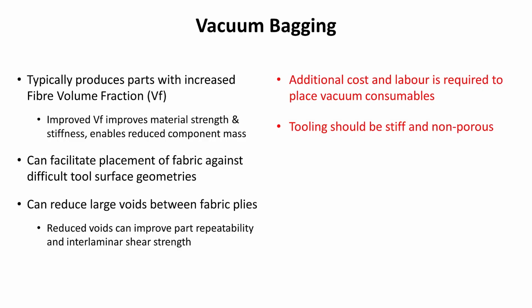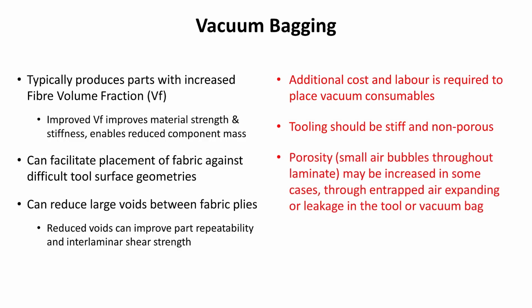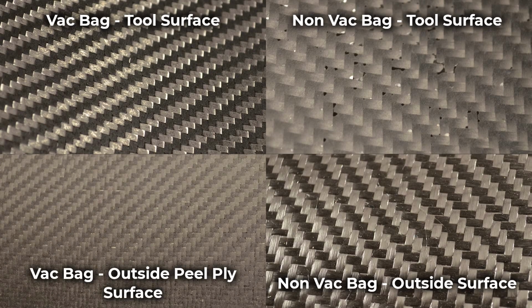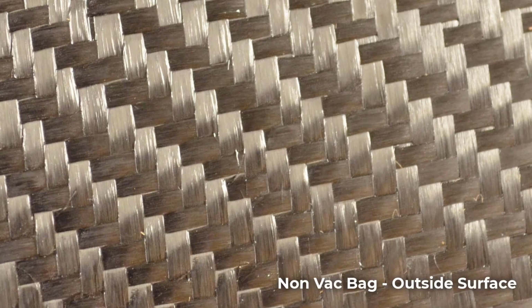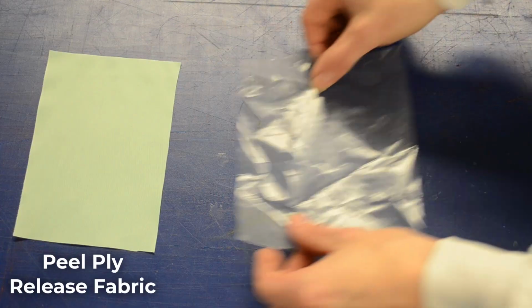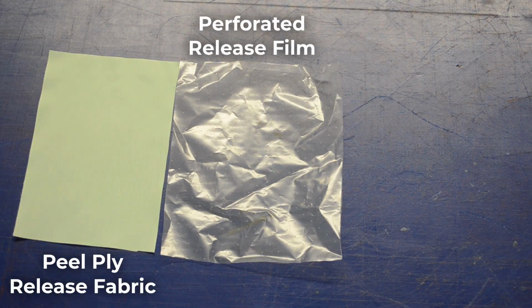Vacuum bags are susceptible to leaks which can draw air into the part and create porosity if not sealed before the part cures. Different surface finishes and qualities are produced by the two processes. If a glossy and somewhat smooth surface is desired on the opposite side of the part, this can be achieved by saturating the fabric with additional resin and curing without a vacuum bag. Different vacuum bagging consumables produce different surface finishes, so with some experimentation, the desired surface may be obtained with vacuum bagging without post-finishing operations.